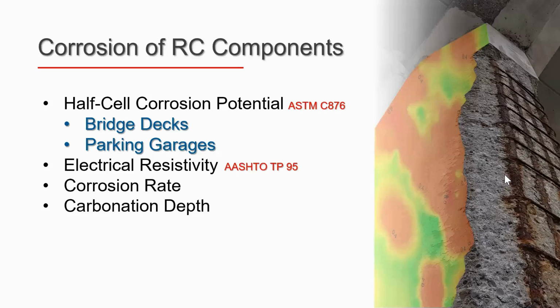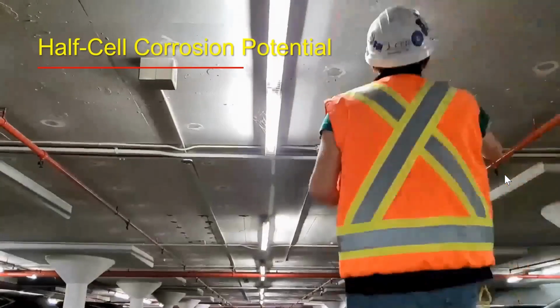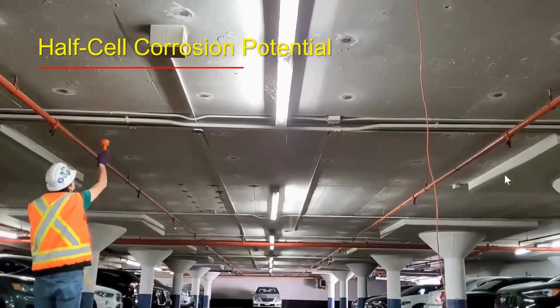Now, there are other tests in this category that can help structural engineers collect more information about the corrosion and the durability performance of concrete. Surface electrical resistivity of concrete is certainly one of the best methods these days to verify the durability parameters of concrete. Corrosion rate measurement, if you are dealing with some sort of service life modeling, can provide information that is pretty useful in terms of planning, and absolutely carbonation depth. When you have a structure that is exposed to carbonation, then these are tests that are relatively NDT, not entirely NDT, because as you saw, there is a need to open up a steel reinforcement at some point and get the connection. But in general, the test is categorized as NDT.